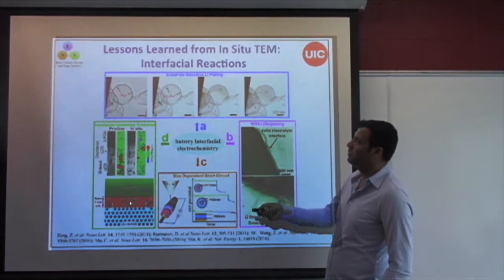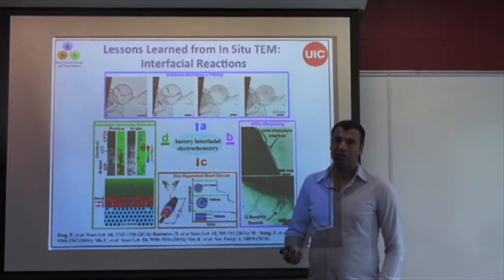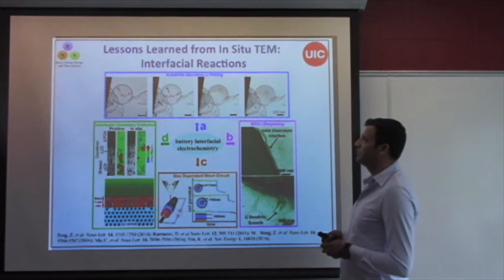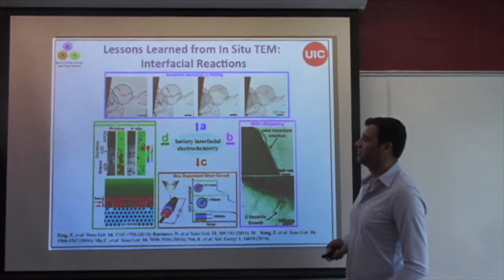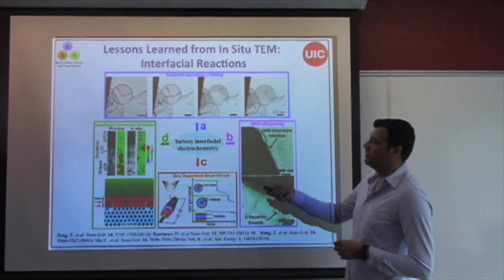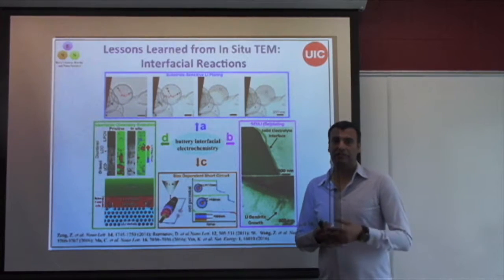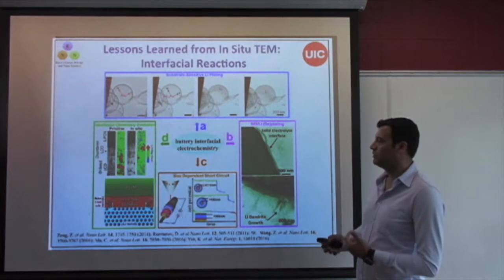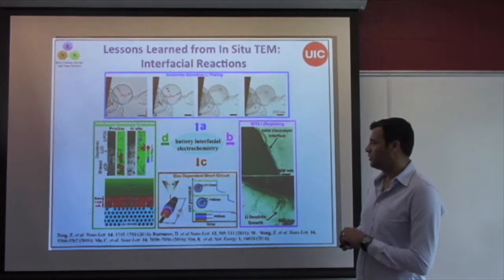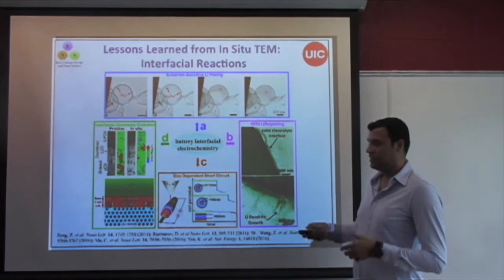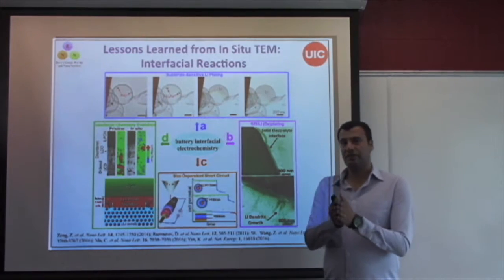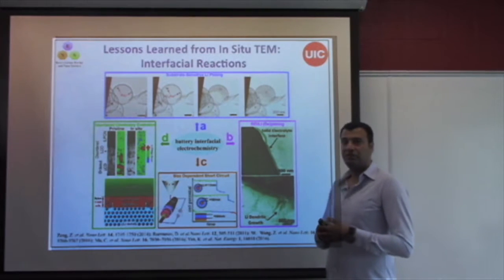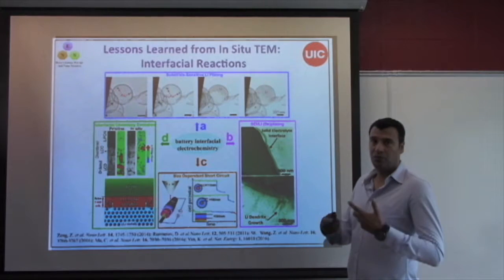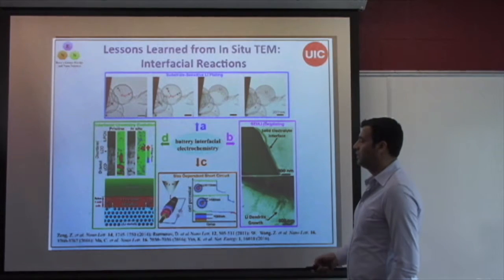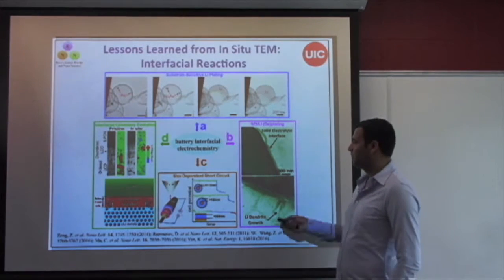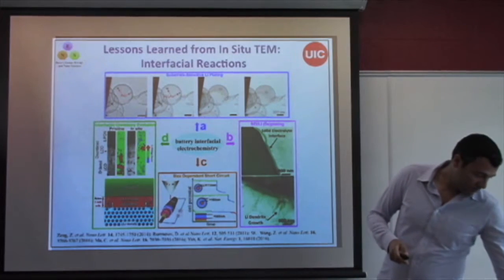Interfacial reactions are very important. Where lithium ions like to nucleate on the surface of electrodes is a subject of interesting research. Whether there is any chemical composition change at the interface between solid electrolytes and an electrode is another contribution in the field. What should be the minimum thickness for the solid state electrolyte, and how the interface between electrode and solid state electrolyte will decompose or fail, has been another interesting research topic, as well as SEI or dendritic formations.